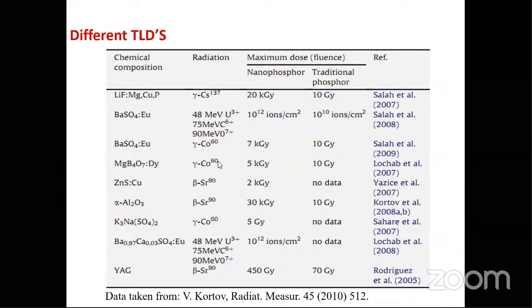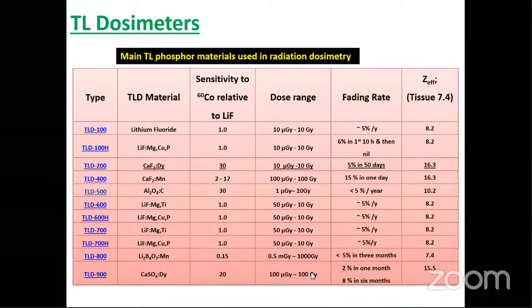These are the recently developed TLD materials. I will skip some of the points here due to time constraints. In our previous slide, what will happen? All the dose range is near about 100 gray, or the maximum dose range is around 1 kilogray. TLD 800 material indicates a dose range response from 0.5 milligray to 1 kilogray, but the sensitivity is very low.